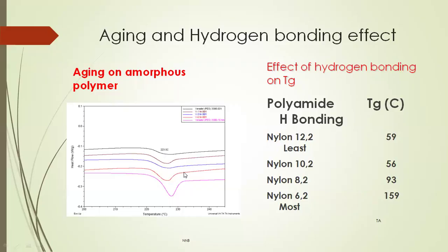You can easily find out whether your material is aged or not by just looking at the TG. This is called enthalpic recovery. And there are n number of papers published on this enthalpic recovery. Again, that is not the topic of our discussion today, so I will not spend much time on it, but just to find out whether an amorphous material is aged or not, you can look at the glass transition temperature. Hydrogen bonding: you have various varieties of nylons available commercially. As you increase the hydrogen bonding, your TG also increases.